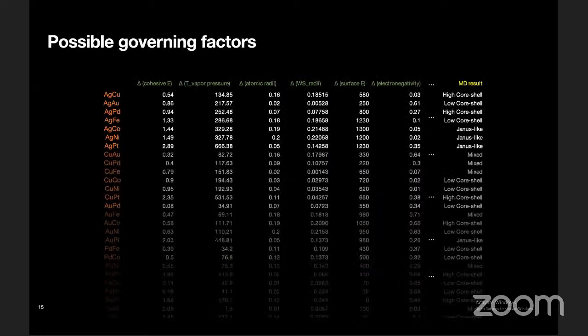In order to do that, we first looked up the possible factors, the features of elements that are frequently mentioned as the governing factors in core-shell preference. For instance, cohesive energy, atomic radii, surface energy, electronegativity, enthalpy of mixing. We ended up considering a total of 8 different features, and for each combination, we wrote down the relative difference in each feature. And we wanted to see which factors are the deciding factors in determining the final structures that we see in the MD results.